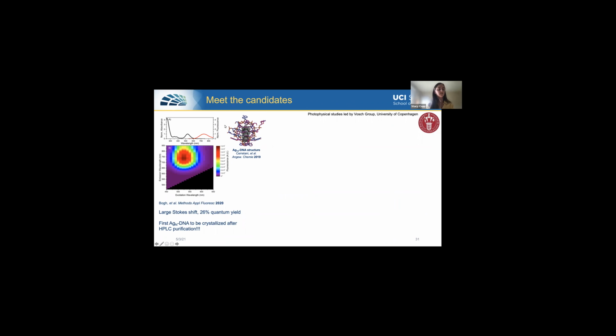Here is one silver cluster that emits in the near infrared at about 730 nanometers. For those who do optical materials, I put in the whole excitation versus emission map if you're curious. This cluster is actually also the one that our colleagues got this structure from. So that's very exciting. And it has a pretty high quantum yield of about 26% for a near-infrared material.